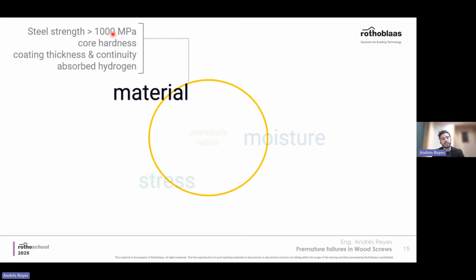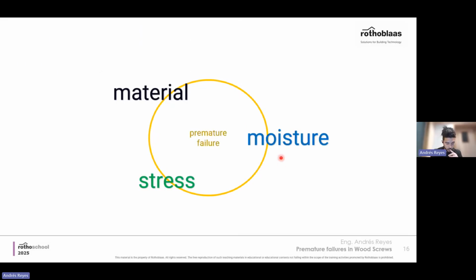And for those types of fasteners, attention needs to be paid to the core hardness, and not only core hardness but also surface hardness. Core hardness is the parameter that is used the most, or limited the most in standards. Coating thickness, continuity, and absorbed hydrogen. So controlling all of this is fundamental. Of course, the material itself is not a cause of or a trigger for failure. You won't open a box of screws with a broken screw because it broke because of any of these things. But it could make the fastener more or less prone to failure in the presence of these two other factors, moisture and stress.